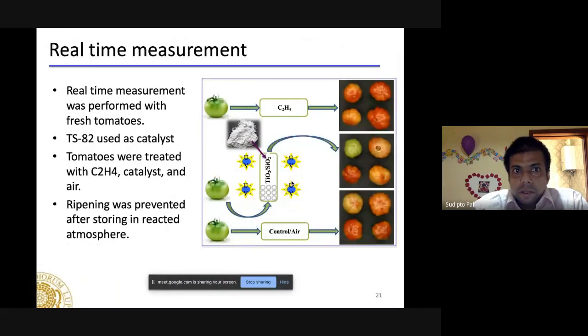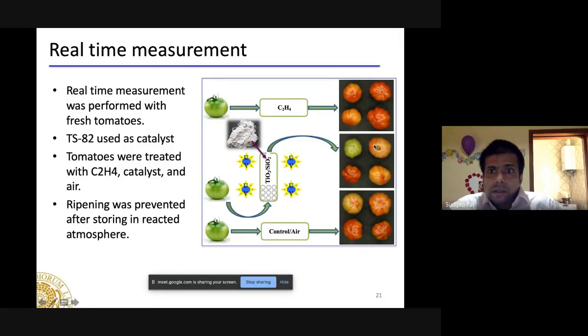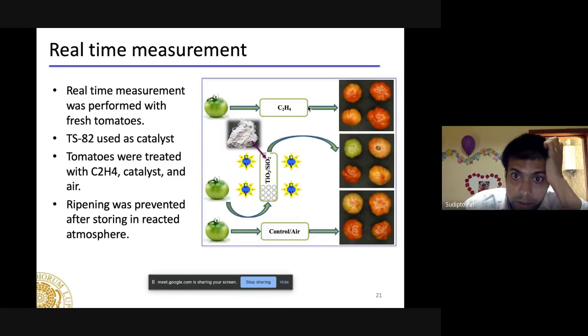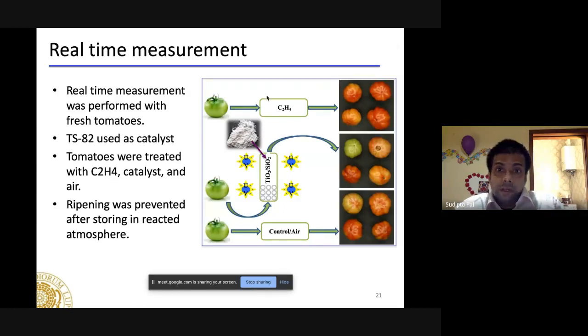And this image shows one real-time photocatalytic measurement with some tomatoes. On the top right, the green tomato is treated with ethylene. So at a certain time, say in 7 days, it is fully ripened. And if we use the photocatalyst, in the middle image, the green tomatoes are still somewhat green, so it takes a longer time to ripen. That means it can decompose the ethylene with the help of the photocatalyst. And with the control experiment, I mean without the photocatalyst, it also ripens very fast.